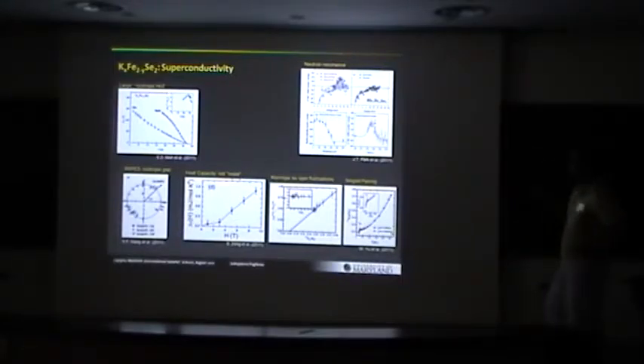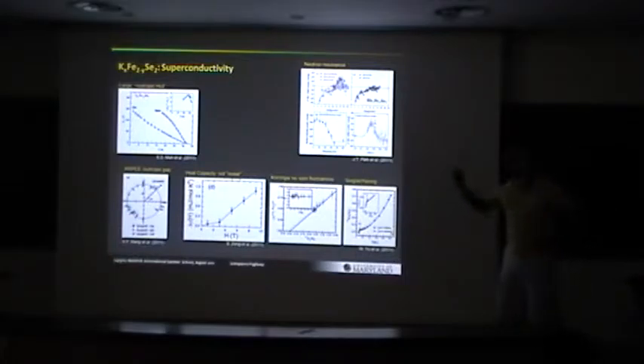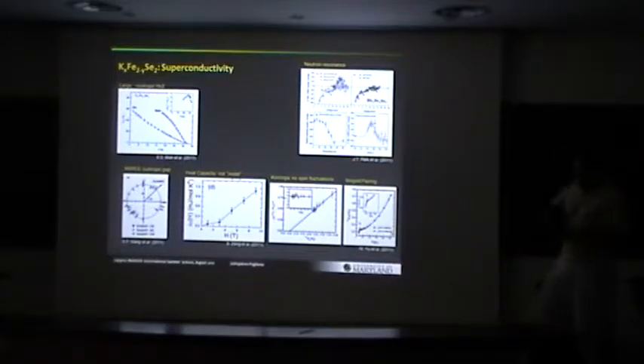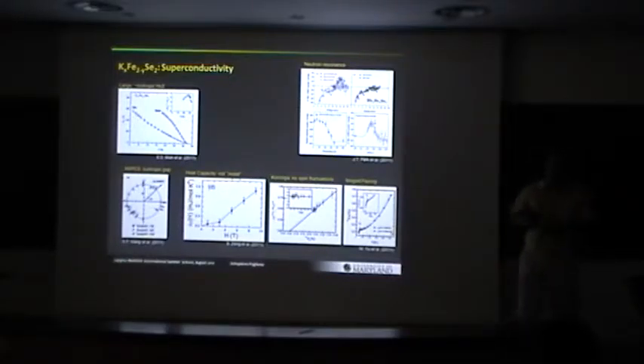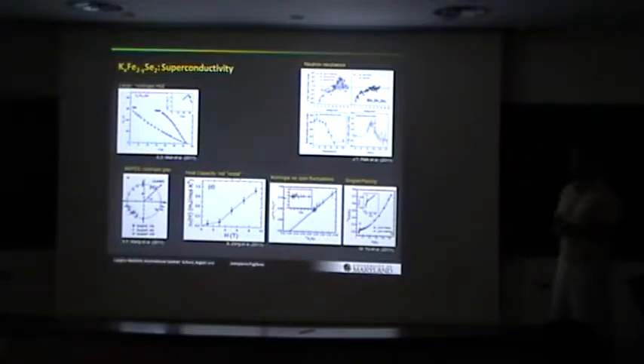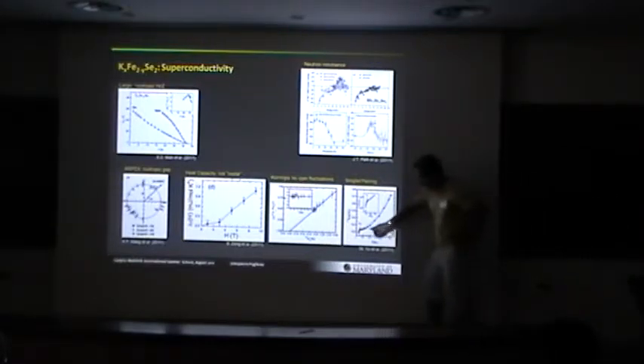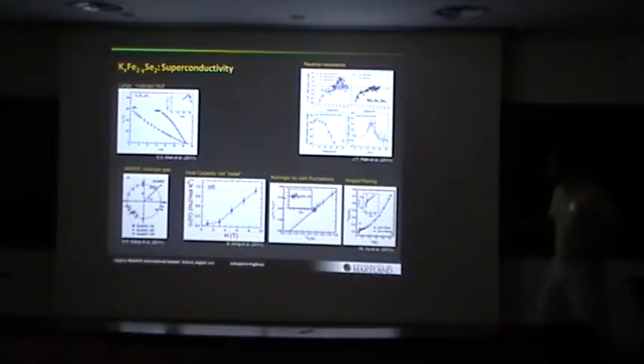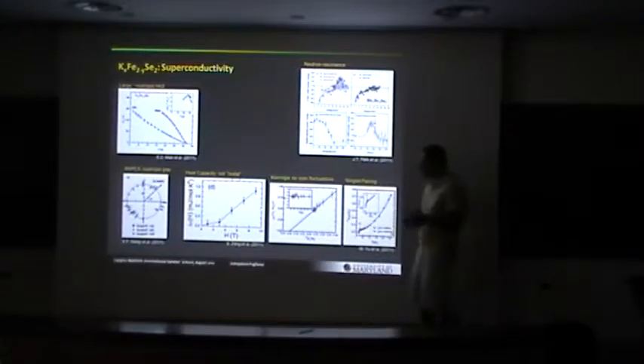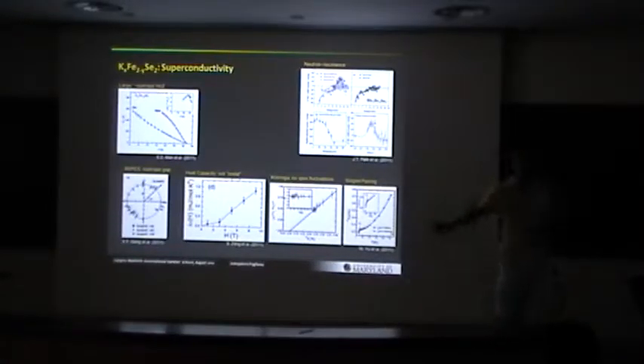What else? There's a neutron resonance that's been observed already. I don't know about the numbers, but this looks qualitatively similar to the other data I showed yesterday, in terms of the appearance of the neutron resonance below TC. I'm not sure about the energy of it related to TC. There's also singlet pairing. There's Knight shift data here showing singlet pairing. And in the normal state there's Korringa behavior, so it doesn't look like there are any effective spin fluctuations, at least in this experiment.